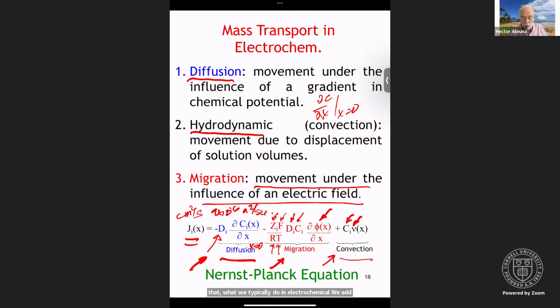One, it lowers the solution resistance. And secondly, it mitigates the effect of migration because it's typically present at a concentration of 100 to 1 relative to your redox active component. So for example, if you have a 1 millimolar solution of a species that is positively charged, but you have 100 millimolar of an inert electrolyte, the migration contribution to the current will be at most 1%. In most cases, that's negligible.